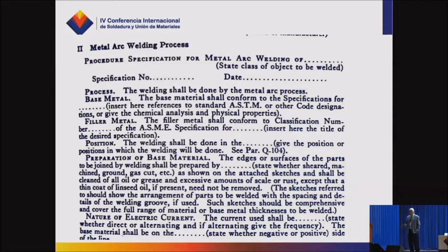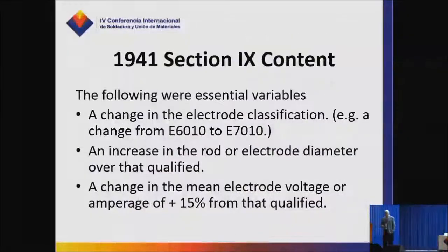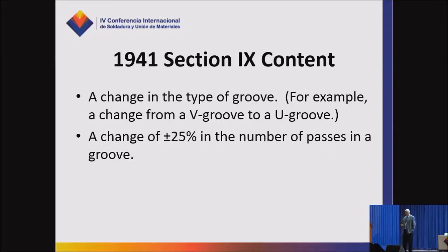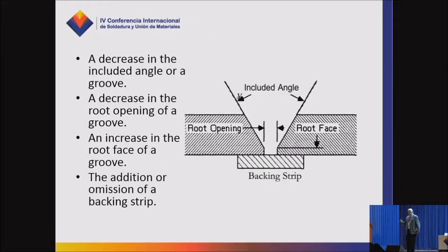Interestingly, the information that was covered in the forms is what we call non-essential variables today. That is information you're required to include in the welding procedure, but does not have to be qualified. The following were essential variables: a change in the electrode classification, an increase in the rod or electrode diameter, a change in the mean electrode voltage or amperage of plus or minus 15% from that qualified, a change in the type of groove, a change in the number of passes plus or minus 25% in a groove weld. You essentially had to qualify what you were going to weld. It went on to talk about a decrease in the groove angle, a decrease in the root opening, an increase in the root face thickness, or addition or omission of a backing strip. If you changed any of those, as described here, you had to requalify.